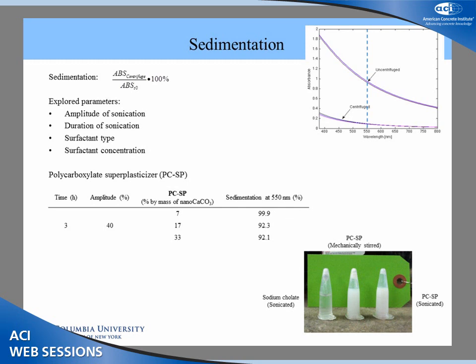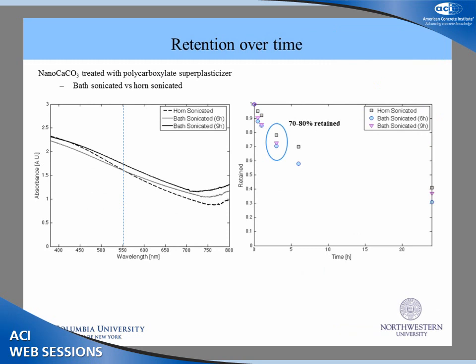So these are the results of just polycarboxylate superplasticizer at a set duration and amplitude of sonication, just varying the addition. So this is in percent by mass of dry nanocalcium carbonate particles. And at 7%, sedimentation is quite high, but as you increase, there is an improvement. And so 90% sedimentation does sound like a lot, but remember, we're subjecting it to a lot of centrifugal force. For the application of casting samples using the suspension, we're more interested in what is the degree of dispersion at the time of casting. And so that's why we recorded retention over time.